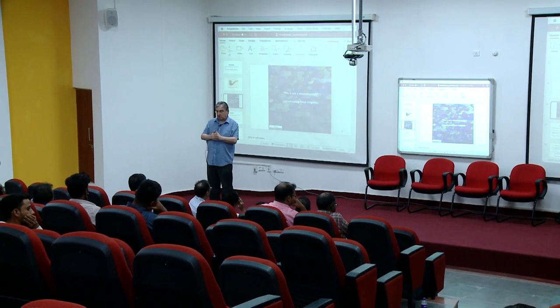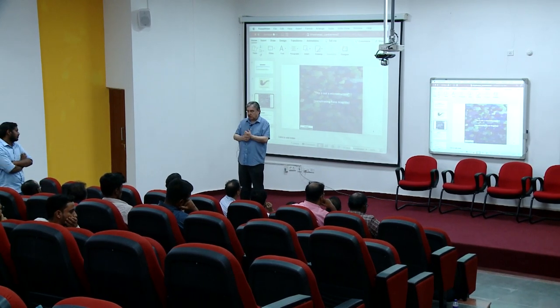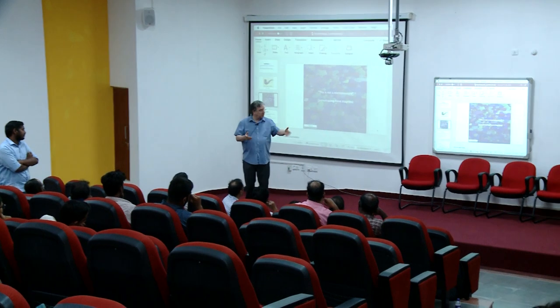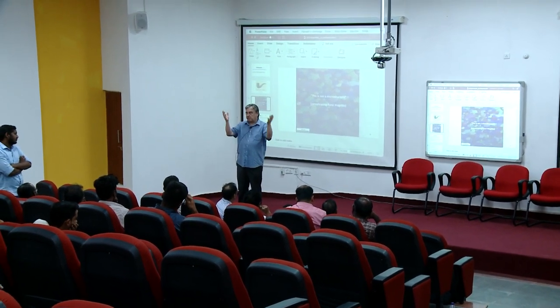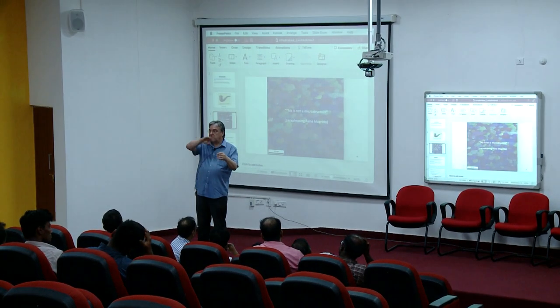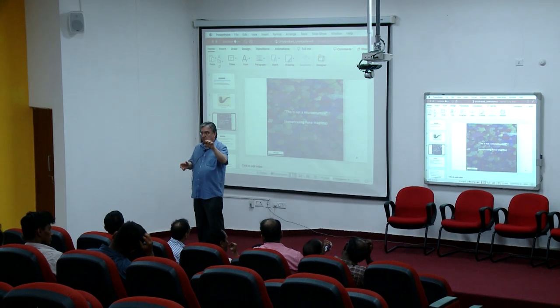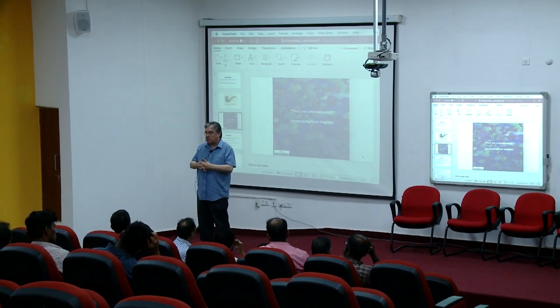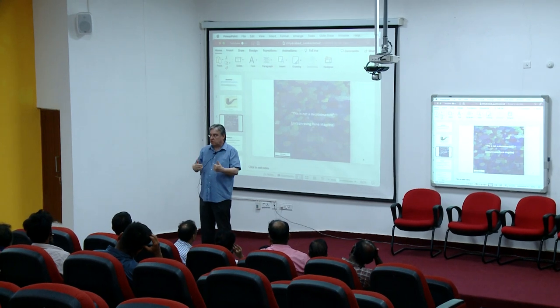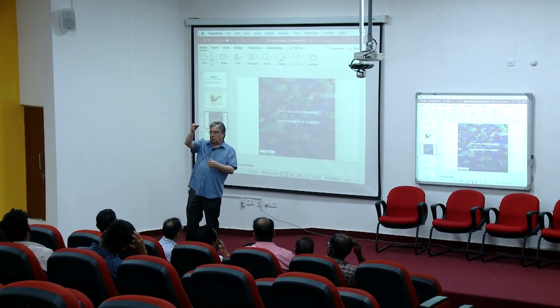We measure such an EBSD with a certain microstructure, of which we assume that it is large enough. For example, 500 by 500 micrometer that has a few thousands of grains in it. Then we have, let's say, 5,000 grains in that. From those 5,000 grains, we are going to make a continuous distribution function. So we shift from, in reality, it's discrete. So you have many different grains in the real material, millions and millions. So we are going to make a continuous function out of that from the one that we have measured. And from that continuous function, we are going to take a sample of n representatives.